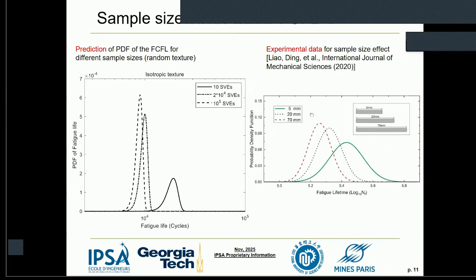So let's see a first order comparison. This is the sample size effect on the fatigue crack lifetime. You can see this is the PDF, in other words, the distribution of the fatigue lifetime in terms of the volume accounted for. This one corresponds to 10 SVEs, a rather smaller volume. And when we get a larger volume, like 10 to the fifth power SVEs, you can see that the fatigue lifetime will be left-shifted. In other words, the fatigue lifetime will be smaller.